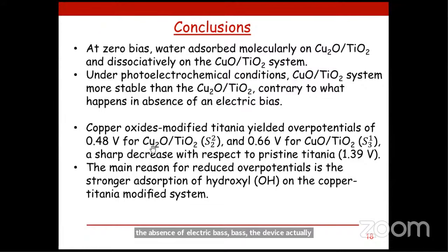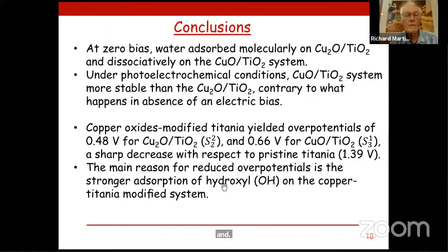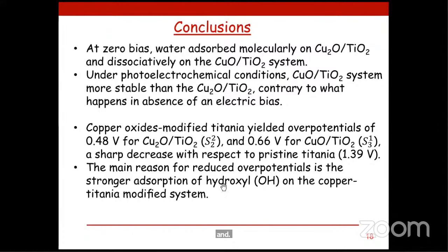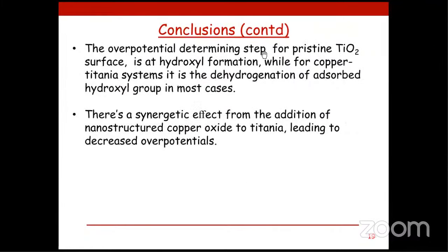is actually true. Then the copper oxide modified the overpotentials, which we actually saw that they reduced to 0.48 volts for the Cu2O TiO2 system, and 0.66 volts for CuO TiO2 system, which is a substantial decrease compared with the pristine TiO2, which had a potential of 1.39 volts. And this is actually due to the strong adsorption of the hydroxyl species on the copper titania modified system. And if you look at the structure of the two systems, it actually supports this kind of conclusion.